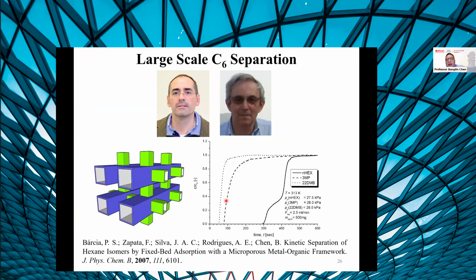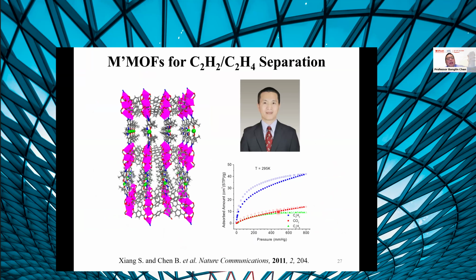So we were kind of the first group to examine large scale separation. Here is the hexane isomer. So at room temperature, this hexane isomer can be well separated. And during our studies, we accidentally realized a mixed MOF material shows quite good separation performance for acetylene and ethylene. And in this example, the separation selectivity is quite good.